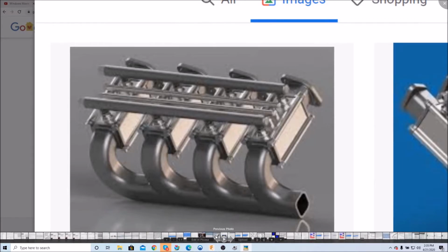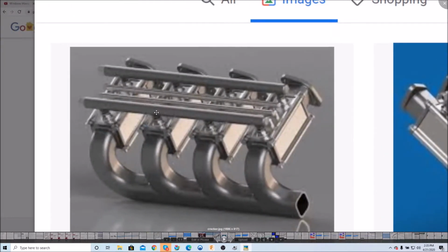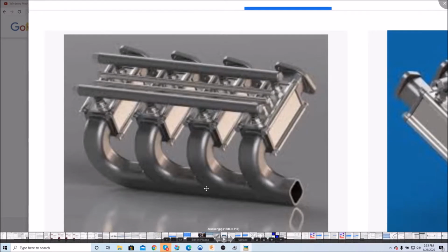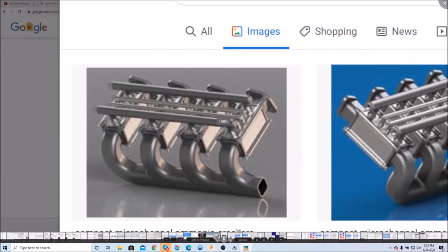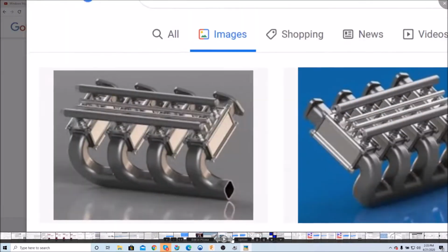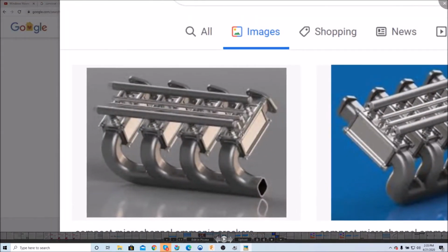This is proven. This was examined, and they found, not with this exact configuration actually, just a tubular catalyst, a tubular cracker, was used and placed on the exhaust manifold. Actually, I think further away from the exhaust manifold, and they were able to achieve 100% decomposition. The other thing is you don't need as high a temperature because we don't need to achieve these high conversion rates.